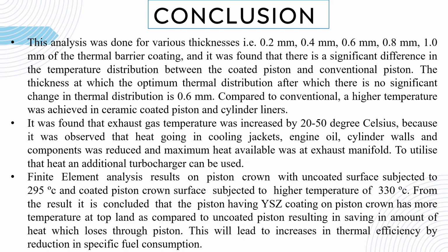To conclude, YSZ thermal barrier coating significantly enhances the thermal performance of diesel engine components. The coated piston and the liner retain more heat, improve combustion efficiency, and reduce the cooling losses. As we can see, there were many thicknesses, like 0.2 mm, 0.4 mm, 0.6 mm, 0.8 mm, and 1 mm, of the thermal coating. The optimal thickness is 0.6 mm, after which the improvement levels off.